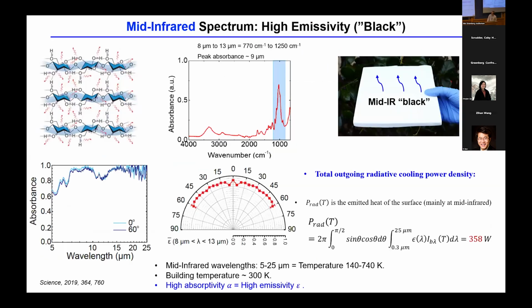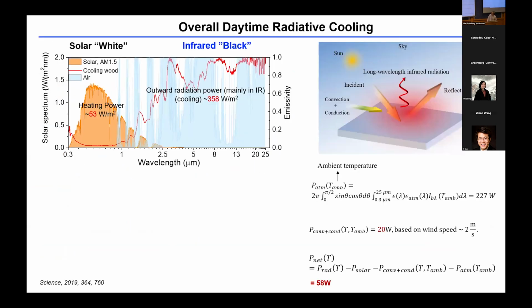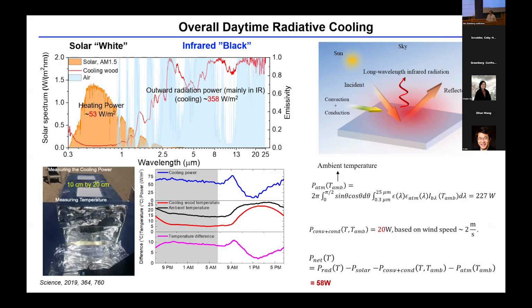It's very white, but in the infrared range, it's very black. Why is that? Because they have a lot of vibrations at the molecular scale, so they absorb energy. That is very high absorption, and also high emissivity. That is why this material is very, very black in the infrared. So if you integrate the visible whiteness that reflects energy out with the infrared blackness that emits energy out, you get a net negative, something called self-cooling. This is a concept that many people now use for making cooling paint, first demonstrated by Stanford Professor Shanhui Fan. He had an ARPA-E project on that topic as well.